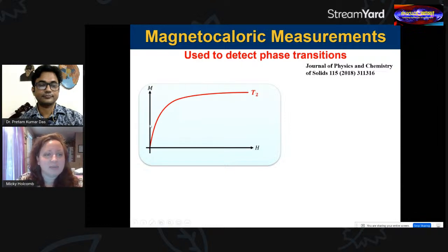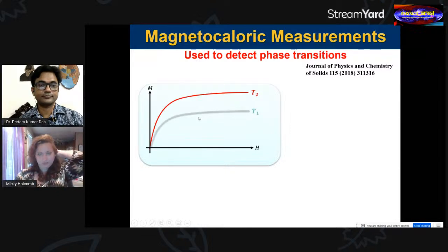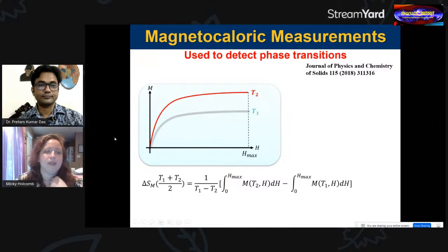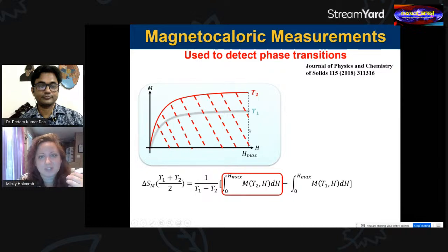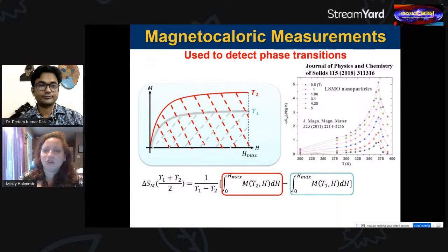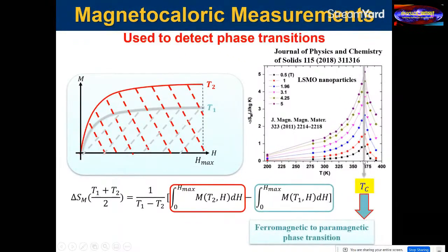So basically, they look at the magnetization for a varying applied field, and they measure at different temperatures. So temperature 1 and temperature 2. And you can actually relate this to the entropy in the system. And so the area under one of these curves at a specific temperature, so the higher temperature would be this range. And then the area under this other curve is this integral here. And then you just normalize this with the difference between whatever two temperatures you're measuring at. And you do a whole bunch of measurements at various different fields and temperatures. And you can plot these lines, and you'll basically get a big peak when you have a transition in your system. So this is the transition from ferromagnetism to paramagnetism in nanoparticles.